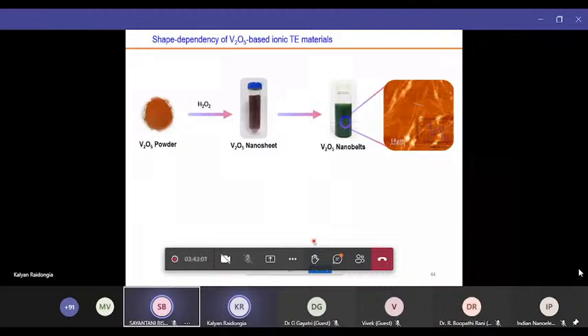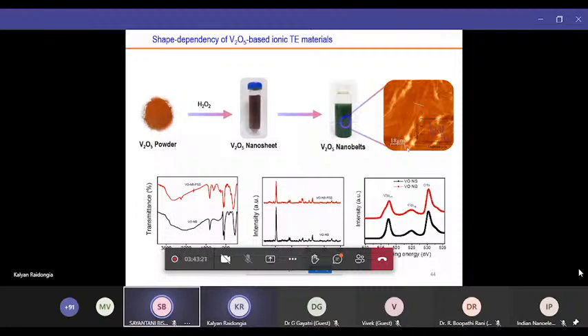Now, to prove that the 2D nanofluidic channels are responsible for this good Seebeck coefficient, what we can do is that 2D sheets can be transformed into rods or belt kinds of shapes. Now, if we take the belts, we don't get those 2D channels where we expect the ions to move through in a well-directed way. These characterizations show that when you change these nanosheets to belts, there is no change in the chemical composition or chemical structure. Only the morphology is changed from sheet to belt.